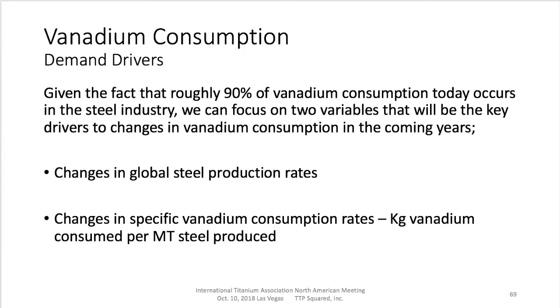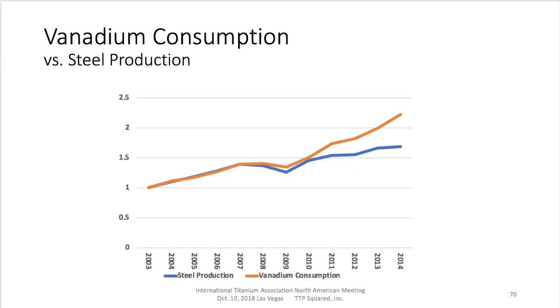Looking ahead, if you want to forecast what's going to happen with consumption of vanadium, there's primarily 2 variables. One is how many tons of steel are produced each year, and the second is how the specific vanadium consumption rate changes. That is, how many kilos of V are consumed per ton of steel produced. And this line shows this specific vanadium consumption is increasing. In summary, vanadium consumption is increasing faster than steel production, which is reflective of the fact that these high-strength, low-alloy steels that use vanadium are very efficient replacements for carbon manganese steel. So we see the ratio of vanadium steels going up year on year.